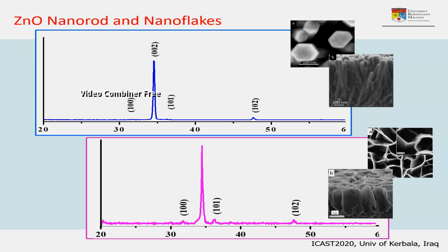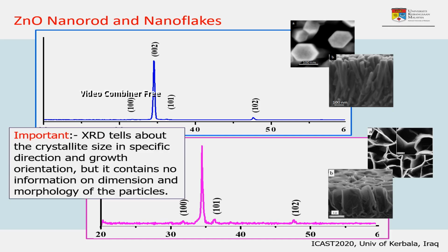Interestingly, if you look at the X-ray diffractogram for both samples, they look very similar. Their similarity carries a very important message. XRD tells us about the crystallite size in specific direction and growth orientation, but it contains no information on dimensions or morphology of the particles. Dear colleagues, my advice to all of you, please be careful in interpreting your X-ray diffraction data.